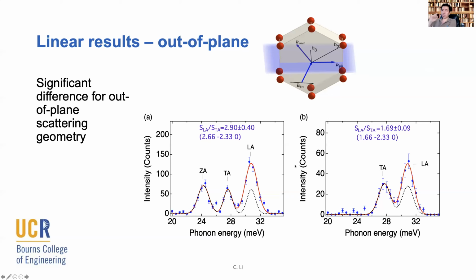So there's a strong indication that we cannot use the existing scattering theory, just like what we did with neutrons. We have to take into consideration that inelastic X-ray scattering is different. We cannot use the same formalism as we did for neutrons, at least for understanding phonons with angular momentum. Okay, and then we thought even further. Does this have anything to do with the polarization? What if we rotate the polarization of the X-rays, or use circularly polarized X-rays? We thought, oh, that might be a fun experiment to work with.